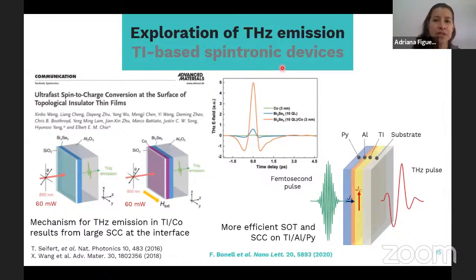So because of the spintronic properties of these multilayers, it has been demonstrated not only with metallic layers, but also with TIs, with metallic ferromagnets, that because of the spin-to-charge conversion of these interfaces, you are able to have emission in the terahertz range, which is interesting for applications. Wherever you have terahertz can be of your interest.